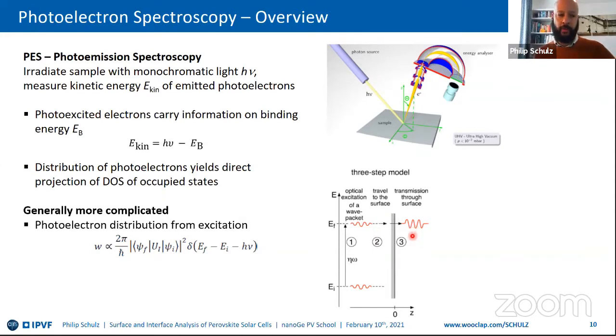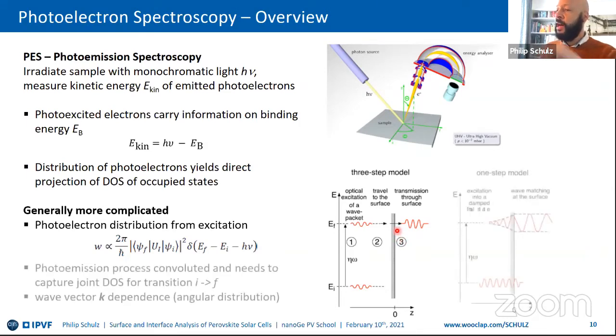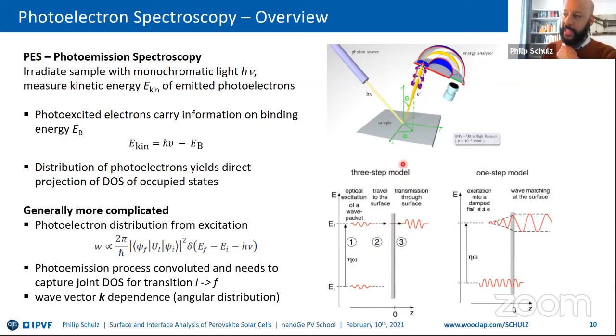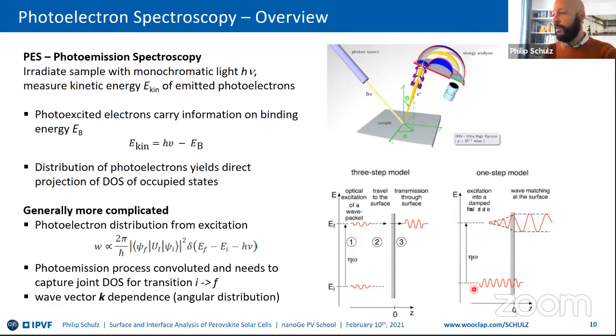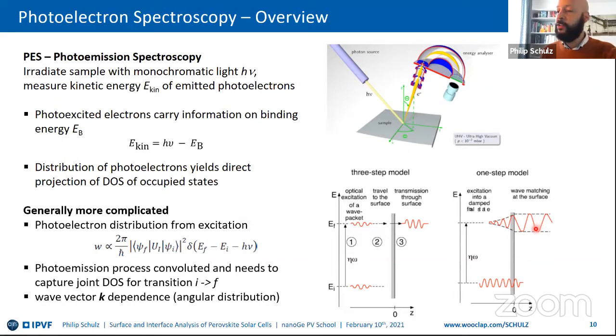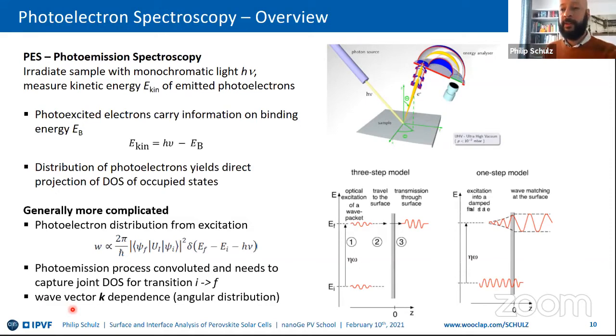Transmission through the surface is critical for angle-resolved experiments, where conservation of momentum must be considered. The three-step model is slightly inaccurate; from a theoretical perspective it is more rigorous to use a one-step model, where you excite the entire system directly from ground state to excited state in one step. Here you have the dampened wave of the bound electron plus wave matching at the surface for the electron in vacuum. This is convoluted but more easily gives wave vector dependence for angular distribution.